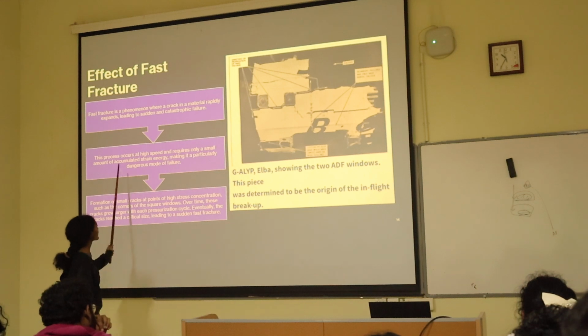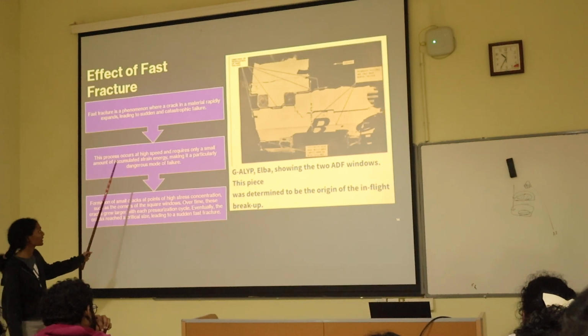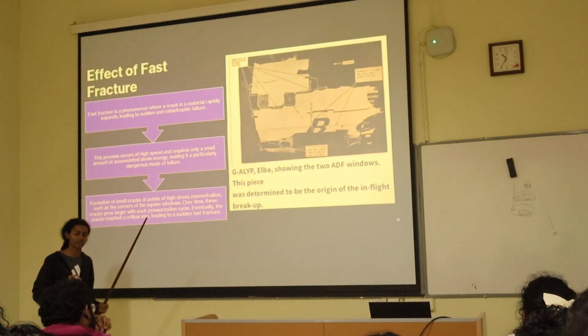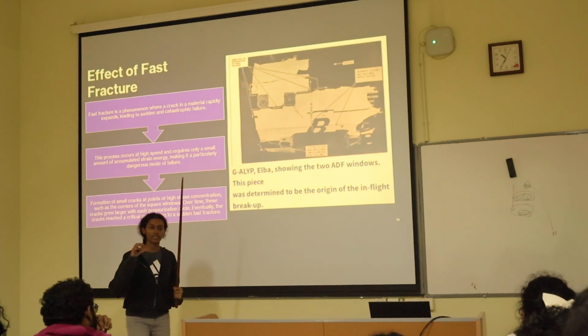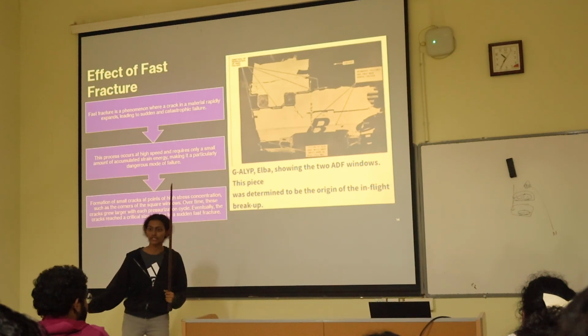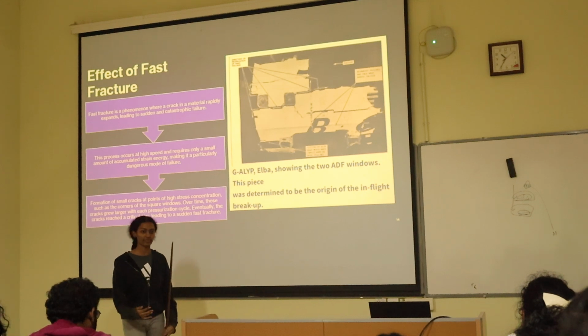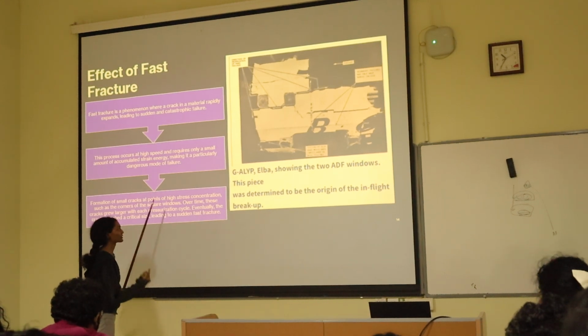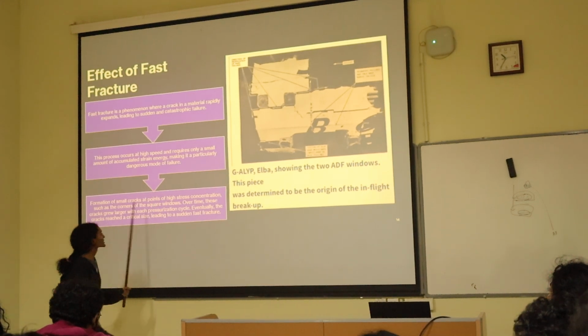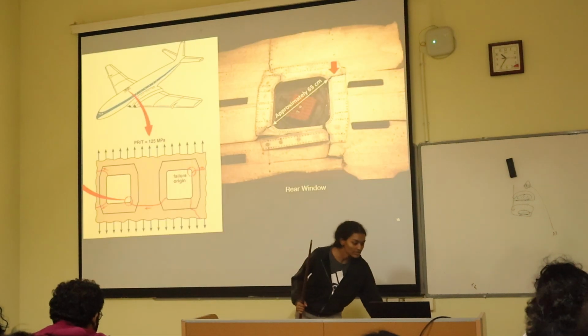Fast fracture is a fast phenomenon, and it leads to catastrophic failure. So already in regions of high stress concentration, the cracks which were already present started propagating, and this led to the failure around the corners of the windows. This is just a summary of what I said.